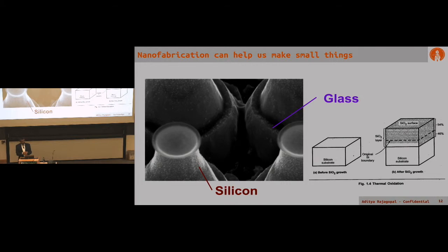As we were building these really small transistors, we found a funny phenomenon. When we exposed these transistors to air, they'd form a layer of rust, silicon dioxide glass on the outer surface. But no matter how much oxygen or temperature we would expose these transistors to, the layer of glass wouldn't grow. This is not an intuitive phenomenon.